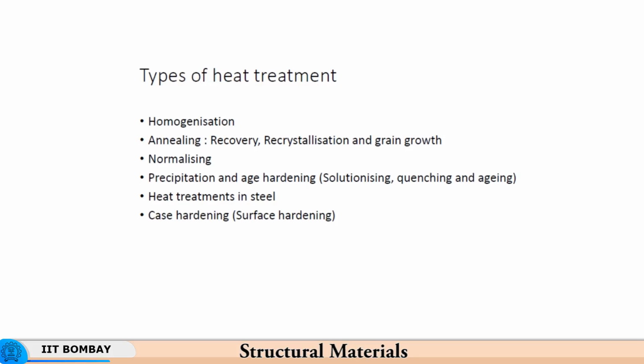So, now if I have grains of a certain size and I have deformed them to a large amount of strain, then I have plenty of dislocations inside the grain, and a high dislocation density, or dense dislocation clusters inside the grain, will serve as nucleation sites for the growth of new grains. So, that is why my recrystallization gets triggered from inside the grain, and the size of the initial grain will get split into a number of smaller grains, and that is how we get recrystallization annealing. And then if you feel that okay, the grain size is too fine, I need a slightly bigger grain size, then I can grow the grains to the size I desire.